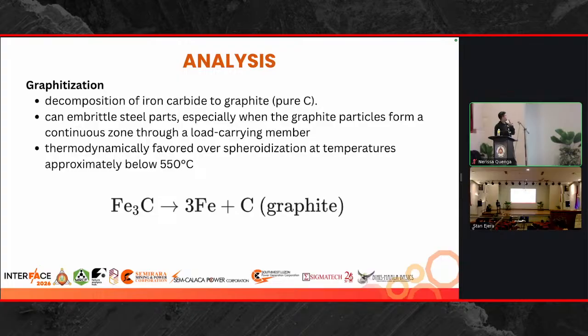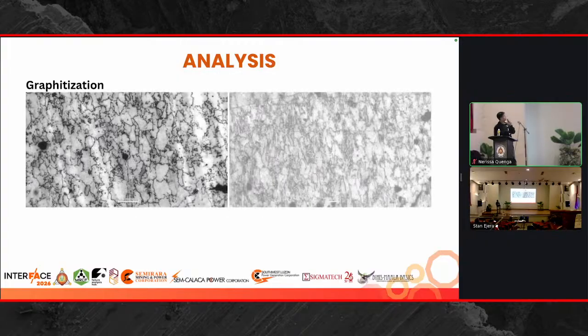It is thermodynamically favored over spheroidization at temperatures approximately below 550 degrees Celsius. So unlike spheroidization, this requires a much lower temperature, but still, this temperature is within the range for the high temperature components that we are examining here in FA Hub. So I'll show you an example of microstructures with graphitization.